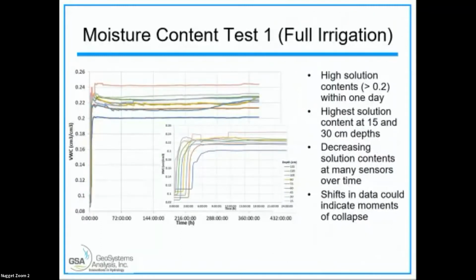Next slide. This is moisture content. So these are all the different sensors. This is kind of a busy graph, hard to describe, but what you see again is this is full irrigation. Within 24 hours, you get a massive increase in moisture content. Again, these sensors are directly underneath the emitter, okay? And what's interesting is that we got solution contents of above 0.2, and in almost all the sensors, except for a few, we got very high solution contents, and then they declined and went down. And I'll talk about that in a minute.